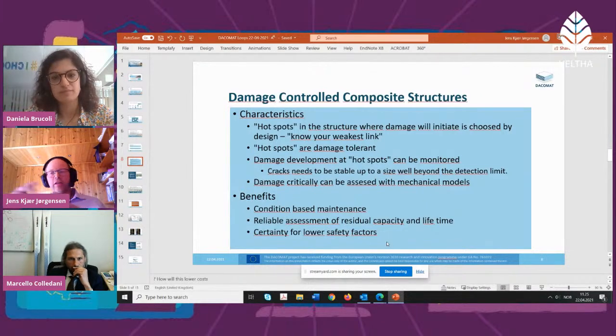And this damage, and eventual damage tolerance at such a hotspot, could be applied, for instance, in a composite at a ply drop. They should be easy to monitor, and that also requires that cracks need to be stable up to a certain size beyond the detection limit of, say, your structural health monitoring approach. And the damage criticality should be able to be assessed with mechanical models, say fracture mechanical models.